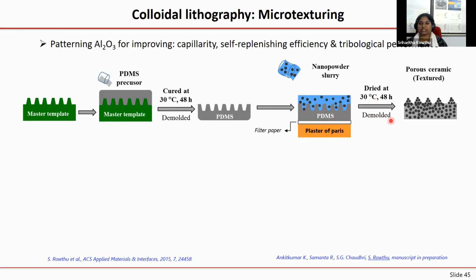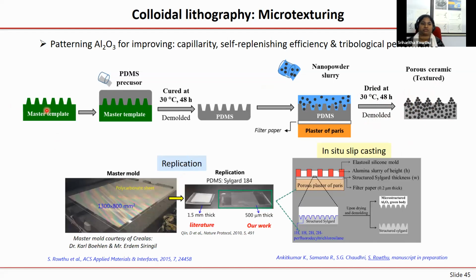Once you dry it nicely, you're able to obtain textured ceramics which have similar topographies as your master template. If you are starting with pillars, then you're going to end up having pillars on your ceramic. But if you're starting with a dimple, then you're going to have dimples on the ceramic. So that's the master template. What I have taken is a laser ablated polycarbonate that we got from a spin-off company from EMPA in Switzerland. This is quite huge. Of course, for my applications, I have just taken sufficient areas.